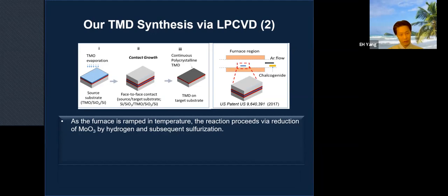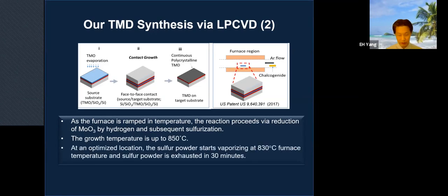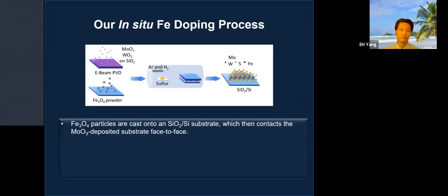Specifically for the hydrogen's role here, as the furnace is ramped in temperature, the reaction process begins with reduction of moly trioxide by hydrogen and the subsequent sulfurization by sulfur. We have a growth temperature here that changes depending on what you want. And at an optimized location, the sulfur powder is exhausted in 30 minutes. Now, in order to dope iron atoms into this moly disulfide lattice, we use iron oxide powder particles cast onto the substrate. And then we contact it with the moly trioxide thin film deposited substrate, face to face.